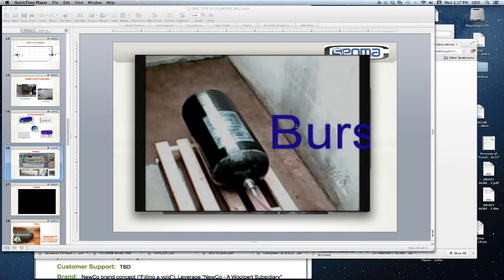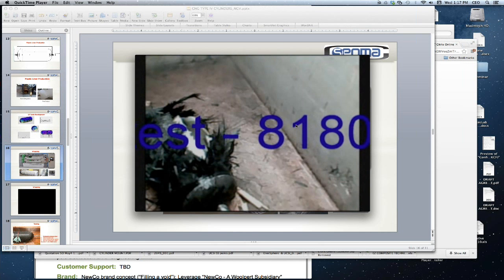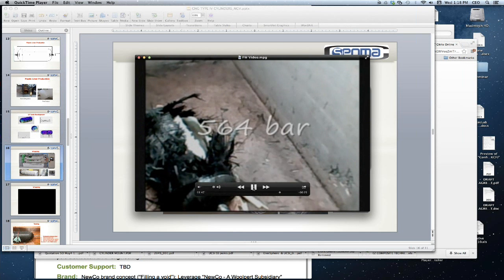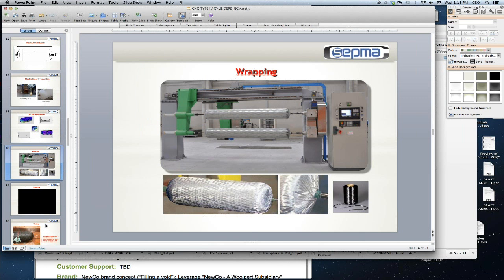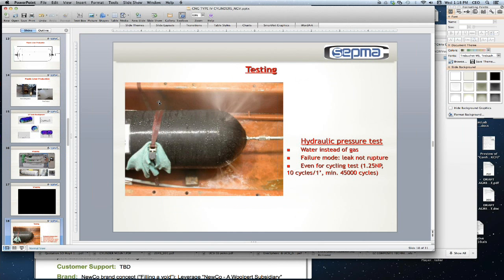This is a first test at about 8,000 psi as described. And we do that typically using just water pressure in a concrete bunker just outside of the plant. So let me continue the presentation by going to what the testing showed you. That particular one was a catastrophic failure. Like I said, the product is usually designed to sustain up to 8,000 psi, which is about a factor of 2.5 over the normal working pressures.